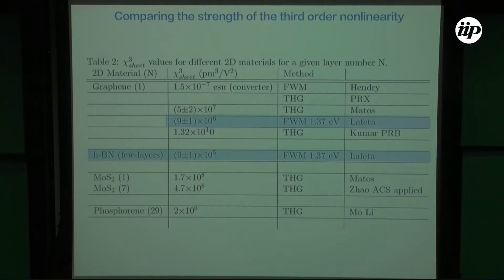We have also characterized the chi3 for graphene and for boron nitride. So chi3 here is around 9 times 10 to the 6. This is in picometer cubed over volt squared. Okay. And for hBN, it's one order of magnitude smaller. Okay, it's much smaller.